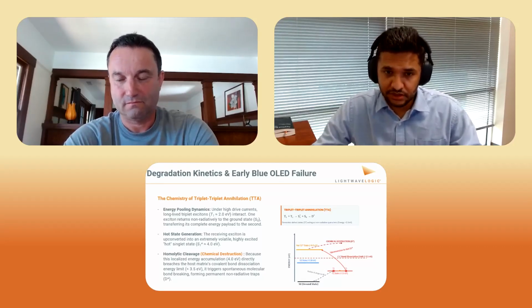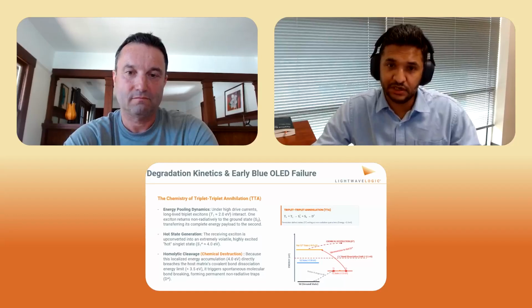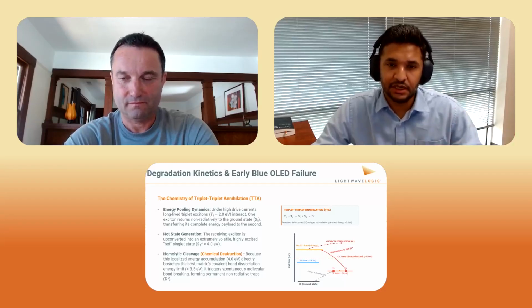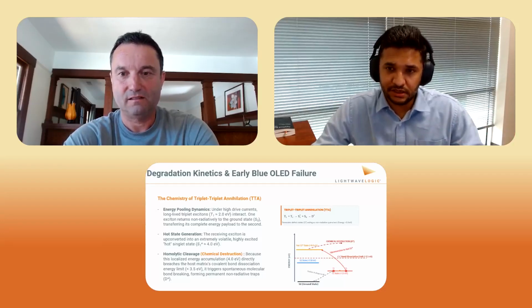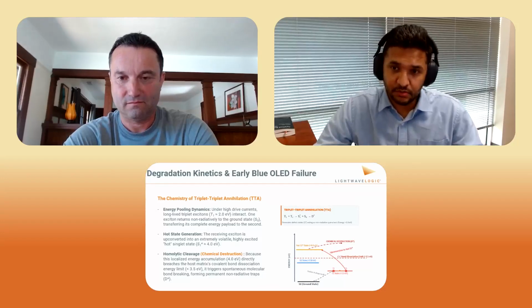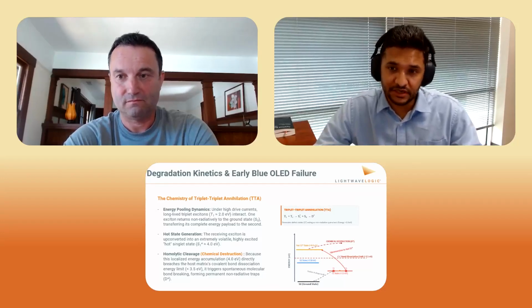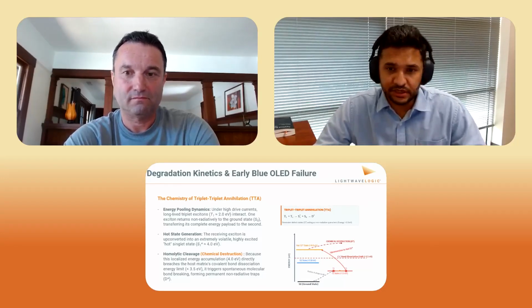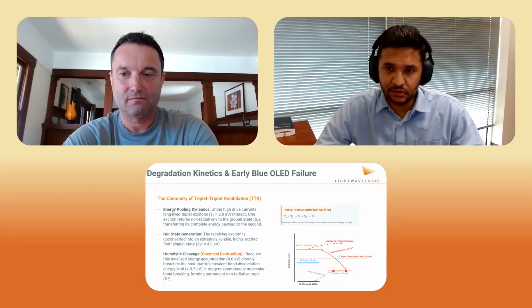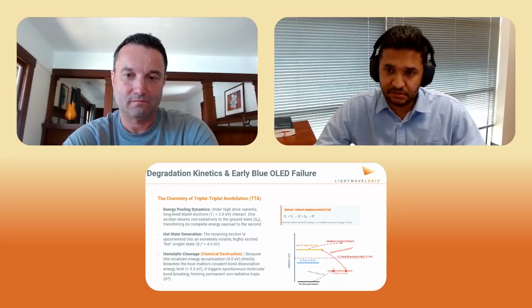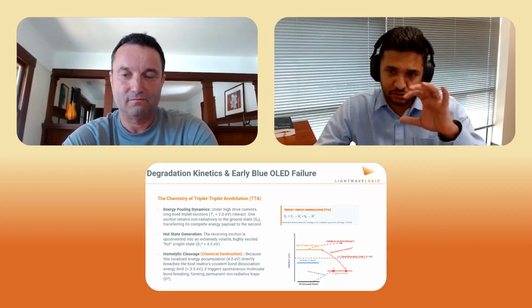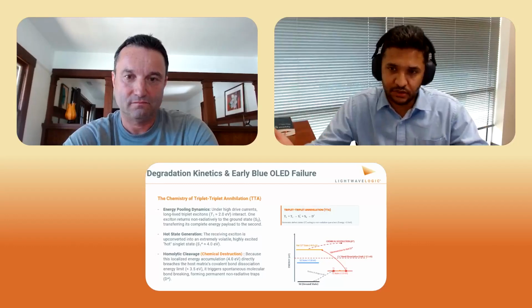And when they collide with each other, you get some of them going to a really high excited state, so much higher than this S1 state that they have really high energy. And that energy is so high that it can actually cleave the chemical bonds of the OLEDs, of the diodes. And once you break the bonds, you get a dead pixel. And then you get dead spots, and those dead spots keep growing, and then you get a fail.